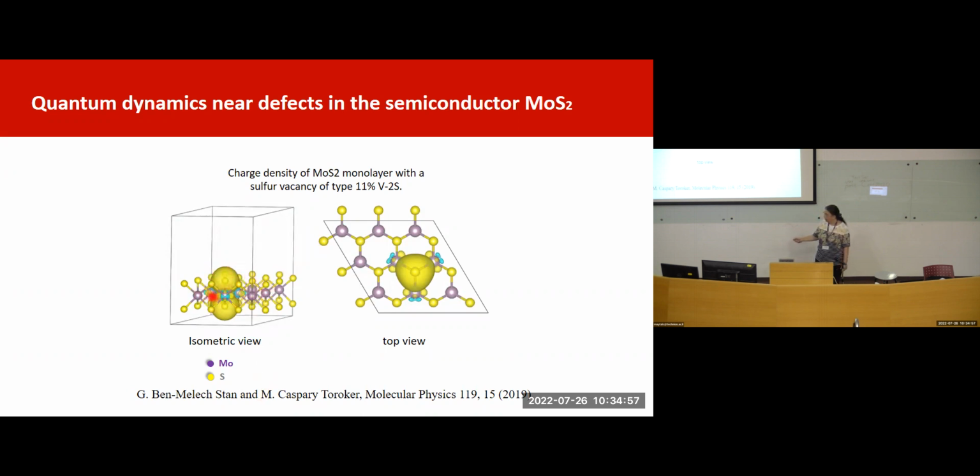From the side view, I'm on a layer of molybdenum disulfide, and on your left side and on the right is a top view. The big yellow bulb is again a charge density difference that we do in DFT calculations to see how a vacancy changes the charge distribution as a result of its absence. So we can see a large deficiency of charge where the vacancy is.